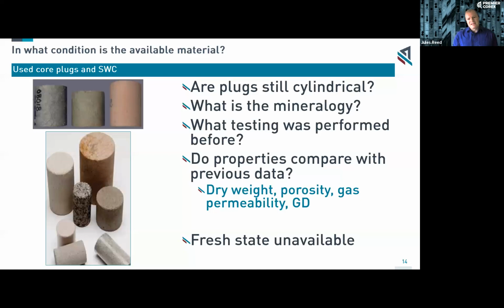We then also need to consider things like the mineralogy of the sample, because there are certain minerals that, together with the testing that has been performed, may have caused problems and may have caused changes to the sample and the sample properties. And one of those might be something like kaolinite, where the cleaning, the flooding, and then additional cleaning may weaken kaolinite booklets. You may then have induced fines migration.